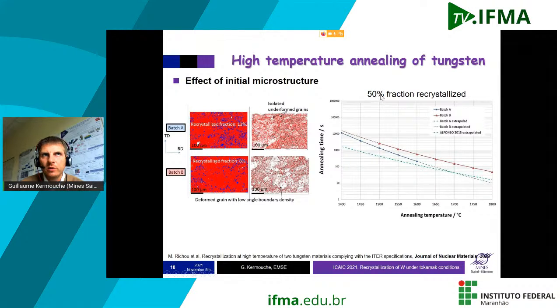So here you can see the results of the heat treatment, at different temperatures. Here this is the annealing time to reach 50% of recrystallized fraction, and here it is the annealing temperature. If you consider the temperature of 1,500 degrees Celsius, clearly to reach 50% of recrystallized fraction with batch A, you need 500 seconds. With batch B, it's about 1,000 seconds.